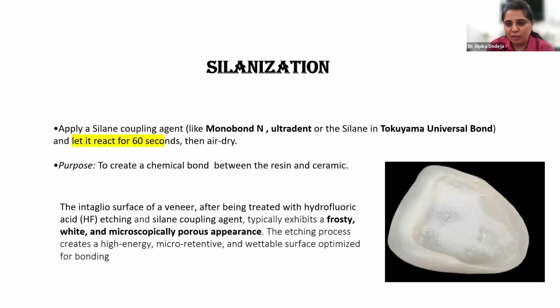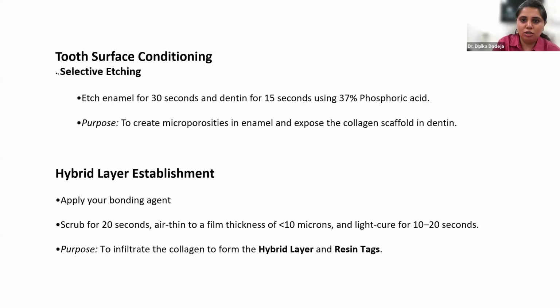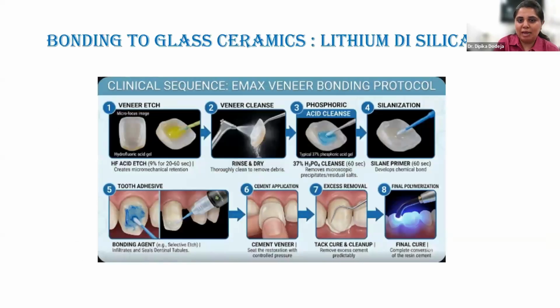So how would you know whether you have effectively silanated the surface? One is appearance. It should have a frosty white and microscopically porous appearance, which shows that these are micro retentive areas which are formed for the bonding with your resin cement. Another way is when you put a drop of water over the silanated ceramic, it will form a droplet. It will not spread over because the silane makes the layer hydrophobic to bond to the hydrophobic part of the cement. Okay, so this completes your preparation of the ceramic.